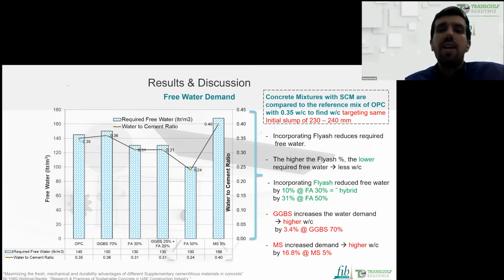I think I missed highlighting the mixes we evaluated with different replacement supplementary cementitious materials. You can see it from here: 70% GGBS, 30% fly ash, a hybrid mix between GGBS and fly ash, 25%, 50%, and 5% microsilica.